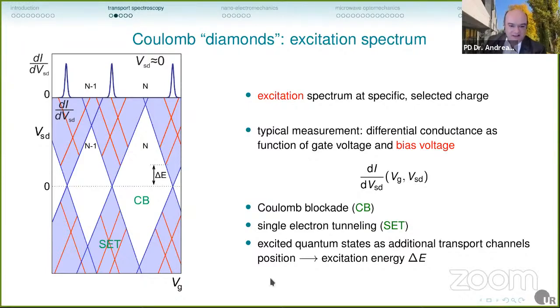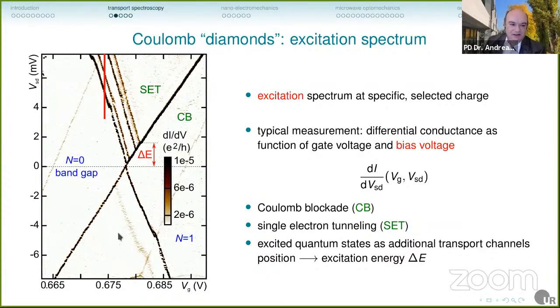Now, this here is a sketch. This here is a measurement. Here we have actually really the band gap, so 0 electrons in the conduction band. Here we have 1 electron trapped in the system. And the lines that we here see correspond to the ground state and the first excited states of 1 electron trapped here in the conduction band of the nanotube.